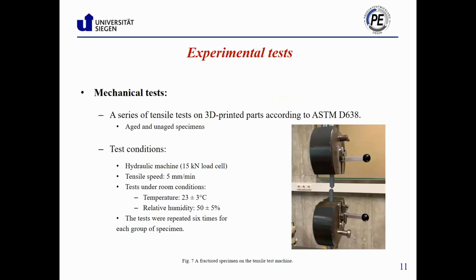After accelerated thermal aging, all aged and unaged specimens were subjected to the tensile test. For the tensile test, we used a hydraulic machine equipped with a 15 kilonewton load cell, and all tensile tests were carried out at the rate of 5 millimeter per minute. The hydraulic operated RAM with the computerized recording facility provides load deflection curves for each sample till it breaks. And in this slide, you can see a specimen under test condition.